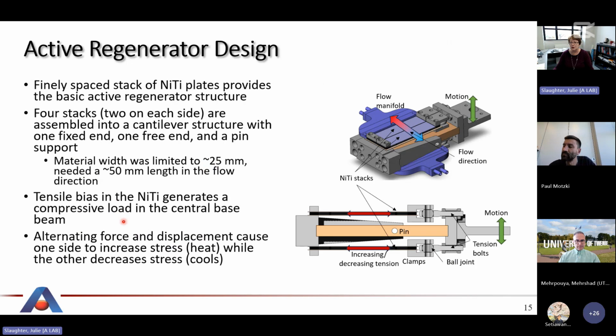So that's great. Now we need to figure out what the mechanical design looks like. What we ended up with is 2 stacks of material on either side, and that was limited by what material we had available to us. We are driving this at this end. We have a rotary joint here that applies tension without any moment to the nitinol. And so that's really just the mechanical details. The flow manifold is a bit of a challenge because you have to flow fluid in and out here. We're not using air. We're using a water-based heat transfer fluid because that has a lot higher heat capacity and a better match for the nitinol. So that is the complicated design we have come up with and built.